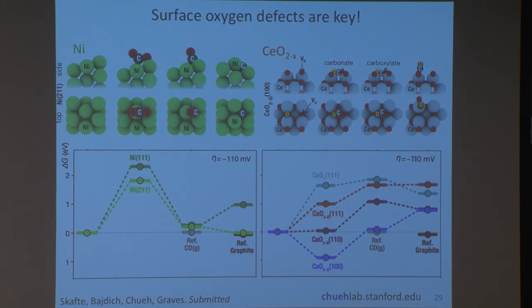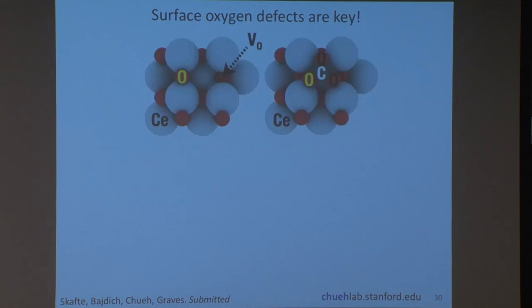And furthermore, if you join the 2 material together, what happens is this carbonate can then oxidize the carbon that's generated here. It becomes an oxygen source locally because you have an abundance of oxygenated carbon. And this is how the material functions. So we're very excited to see this because in the past, it hasn't been possible to follow the reaction pathway of turning CO2 to CO and avoiding carbon deposition. But by combining the operando characterization with the theoretical calculation, we're gaining some insight into the energetic landscape of turning CO2 into CO selectively. And to mention this one more time, the key is the missing oxygen on the surface.